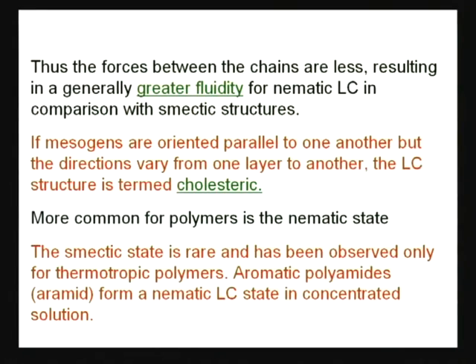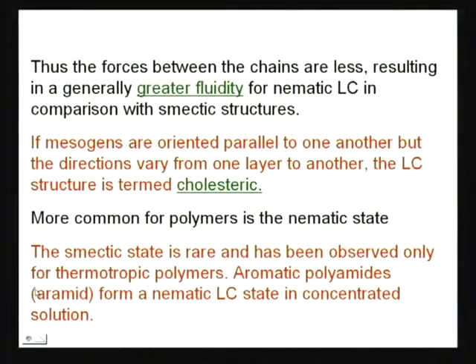That means, for multi-layered configuration, we can get this Smectic structure. More common for polymers is the nematic one. The Smectic state is rare and has been observed only for thermotropic polymers by melting only. Aromatic polyamides, as I showed there, aromatic polyamides or polyimides. Aromatic polyamide means aramid, it is a Kevlar fiber, which is used for making bulletproof jacket. That means, it has capability of absorbing huge impact without failure. That property comes from their molecular alignment.